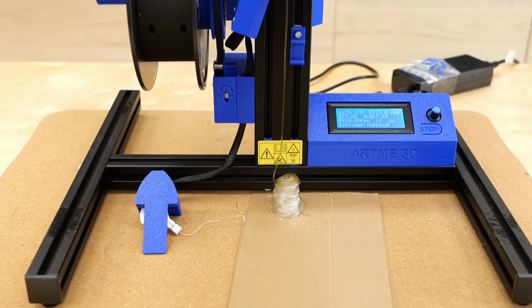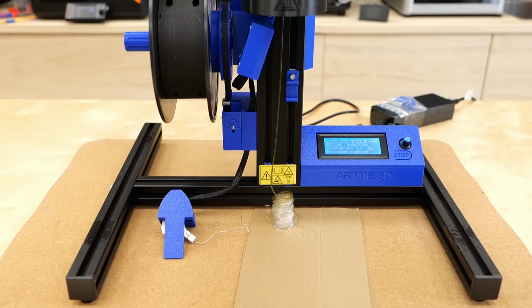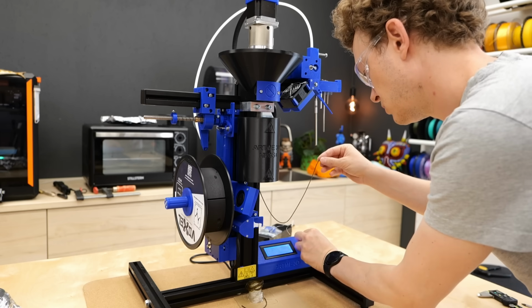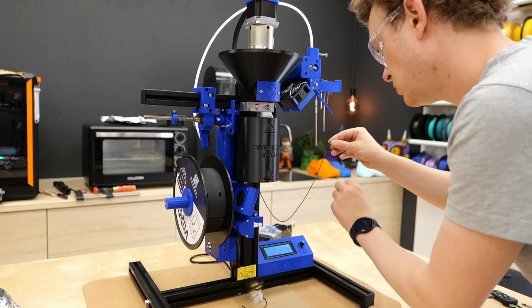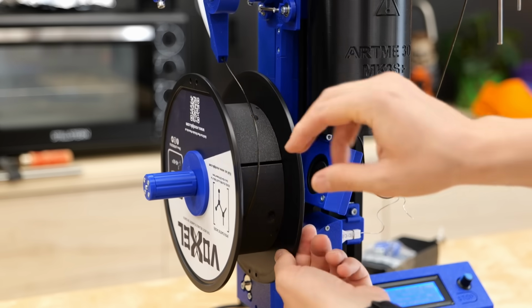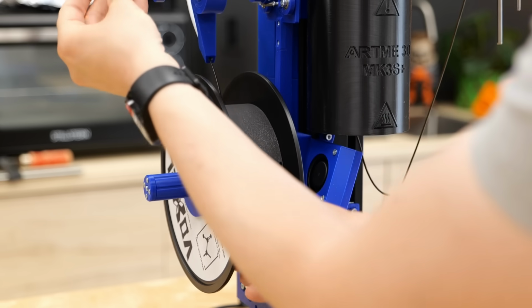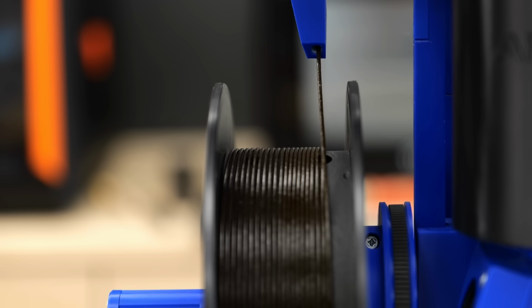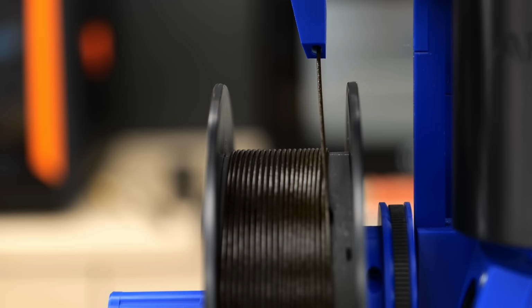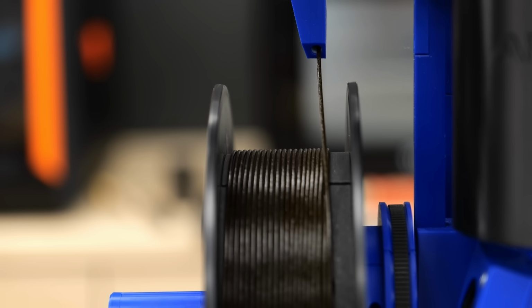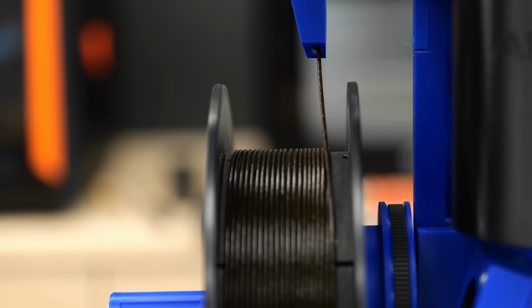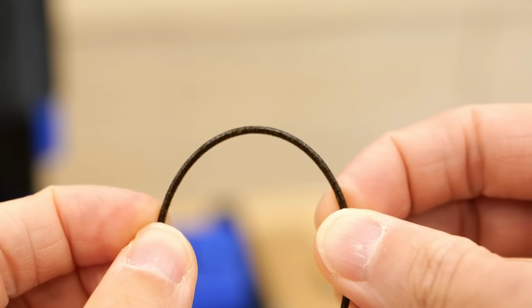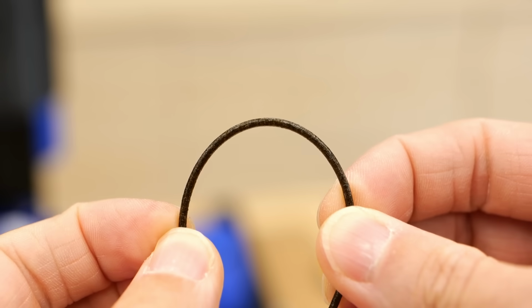After the old material was purged out, I quickly got a very good looking filament that I directly started winding. After the diameter looked good, I connected the end to the spool and it started filling the roll. At first glance, I didn't see any agglomerations in the material and the filament seemed to have a very even distribution of particles in it. It also was by far not as brittle anymore as the last batch and formed a really nice wind.